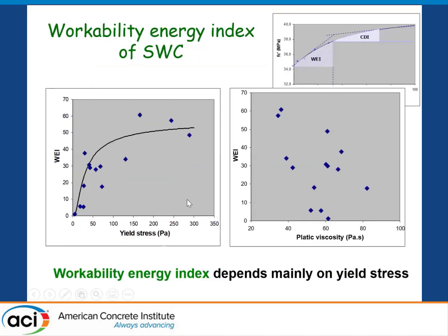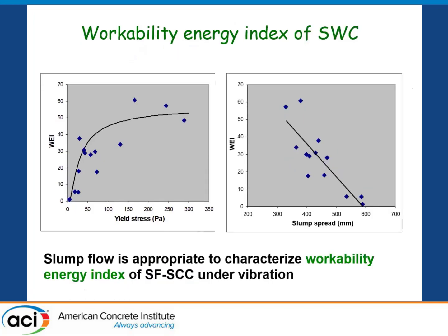And here we are trying to correlate many different mixtures, the workability energy index to yield stress. And you can see that it's very much related to yield stress and not so much related to plastic viscosity. There's a trend, but it's a weak trend. It's really dependent on the yield stress. The higher yield stress, the higher the energy that you need, i.e. you have to consolidate the concrete more to achieve self-consolidation.